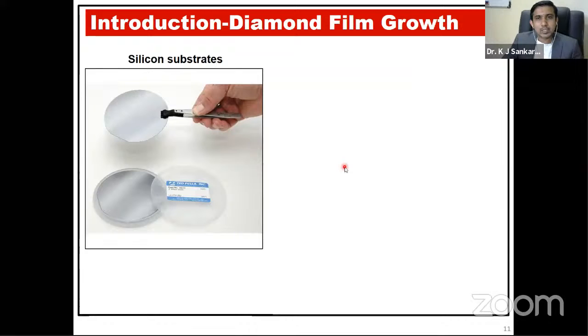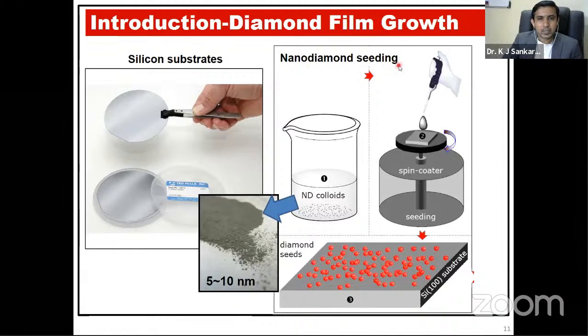Now I'm going to the diamond film growth, how we are growing the diamond film. These are the commercially available silicon substrates, and we need to do nano diamond seeding. Why do we need the nano diamond seeding? Because silicon substrates are used mostly for microelectronic devices, and if you use a diamond film on silicon, it has very good adhesion between diamond and silicon because of the low thermal mismatch. But silicon doesn't have any diamond on its surface. So we need to seed nano diamond particles on the silicon substrate.